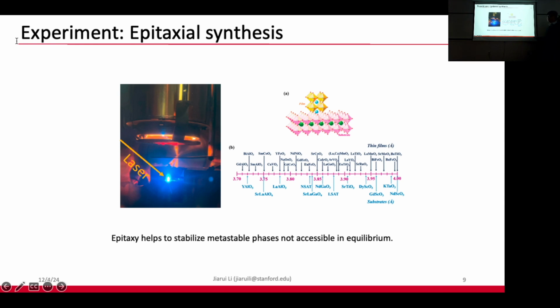And this is a photo of such a synthesis technique called pulsed laser deposition, where a very high power laser comes in and hits a raw material target, and it excites a lot of active atoms, and they get deposited on a pre-selected substrate. So this is a perovskite lattice substrate, and we deposit a lot of atoms on top of them, and this epitaxial relation requires that the atoms form with the same lattice symmetry as well as lattice constant as the substrate.